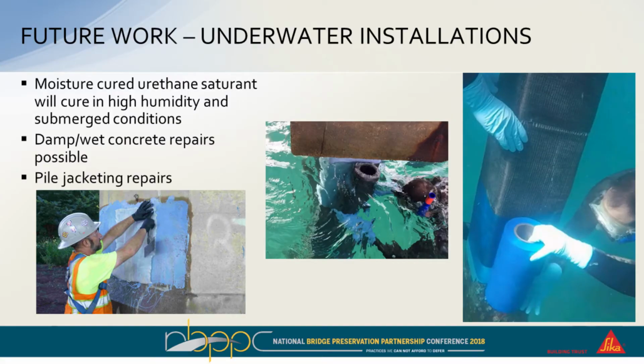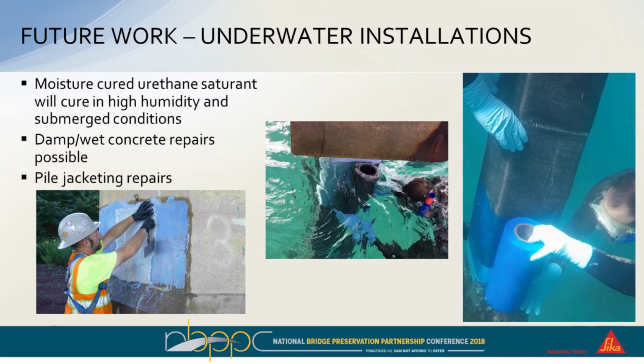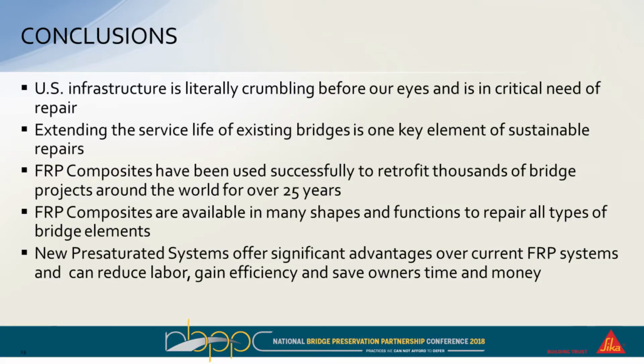And then finally, some future work. Since we have moisture-cured resins, we can also now look at the use of these materials for underwater or completely damp or even splash zone applications. So the moisture-cured urethane resin, we know it will cure in high humidity and submerged conditions, also for damp or wet concrete repairs, and also for use in pile jacketing, which is another big application either on concrete or timber type piles.